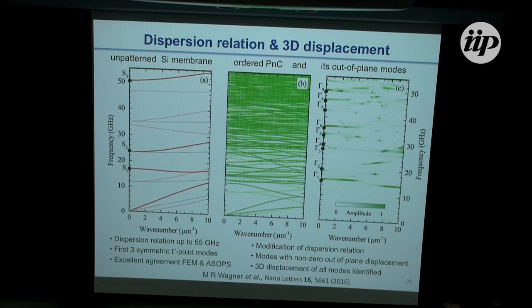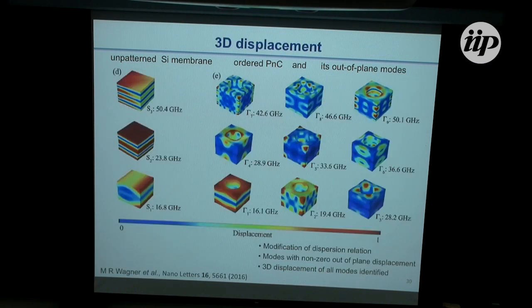So yes, as in the previous case, we have more evidence of modified dispersion relations. There are modes which have a non-zero out-of-plane displacement. These are particularly here. And there are 3D displacements of all the modes identified as shown here. So these are the modes depicted from FEM, the unpatterned membrane, and then the modes of the ordered phononic crystals, which go from 16 gigahertz all the way to 50-something gigahertz. And so these are fairly well described and documented here, amplitude and polarization.